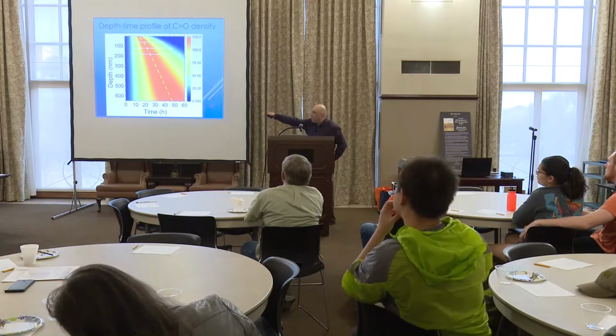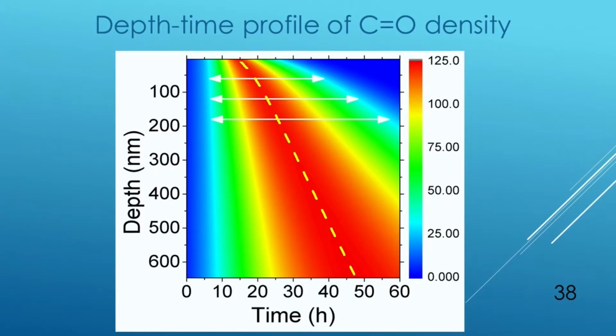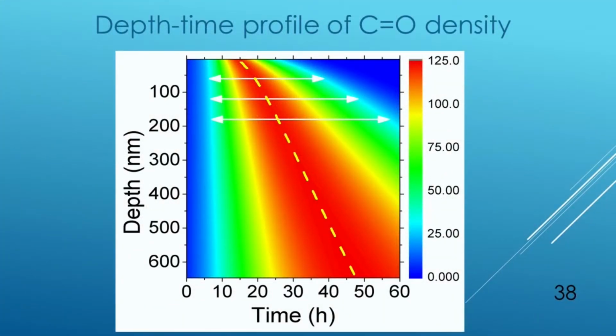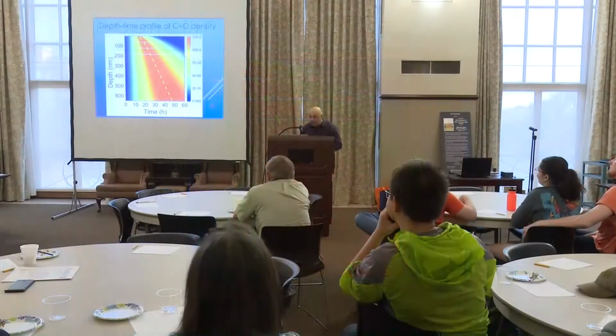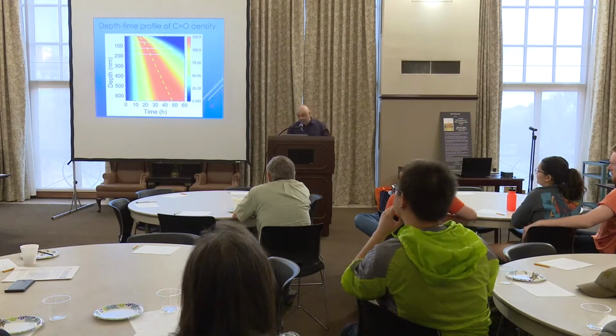If we look at somewhere deeper, things actually happen slower because the top layer is shadowing the solar light. Basically, though, eventually the solar light comes to the deeper layers too. The way it happens is, first the top layer is just gone, and then the second layer gets actual solar light, then it's gone, and the third layer later and later. And if you look at this maximum carbonyl density, it actually goes linearly with the depth of the film. So this model was also explaining how photodegradation was happening through the depth of the film, or the depth of the plastic, which was not really known before, I guess.